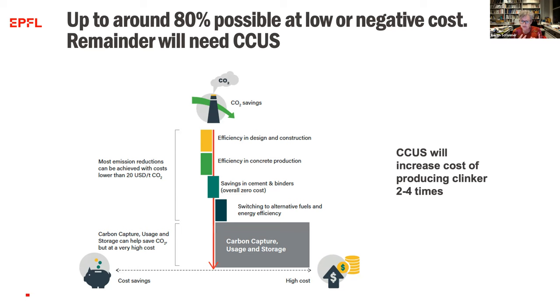Eventually, you're going to need some measure of carbon capture and either usage or storage, but here we see a really huge change in the cost. And that's the important point. We need to maximize the savings we can get from these things up here, which have very low or even negative cost, to minimize the amount of carbon capture. Because carbon capture is going to increase the cost of producing clinker by around 2 to 4 times.